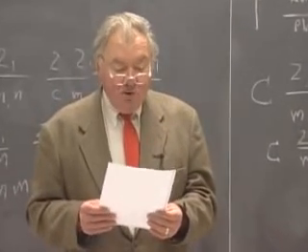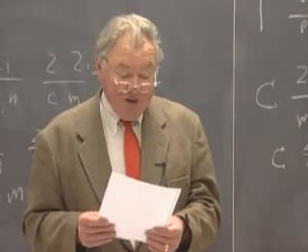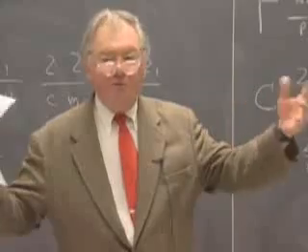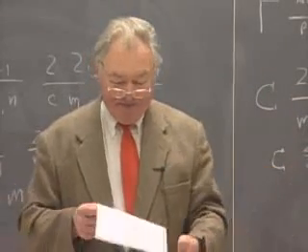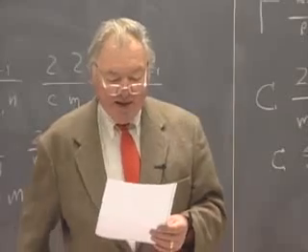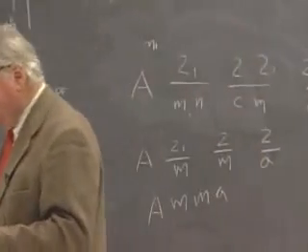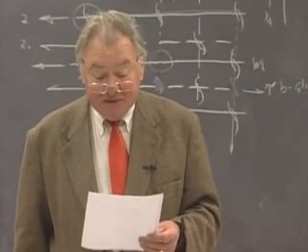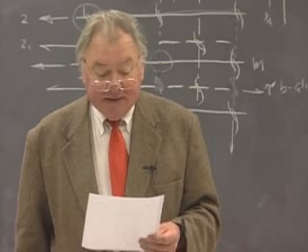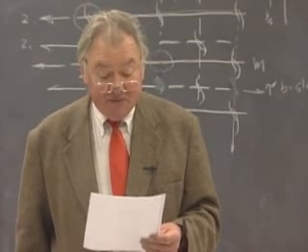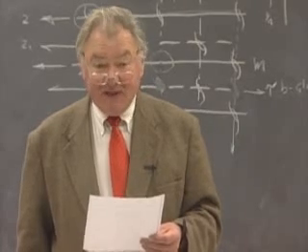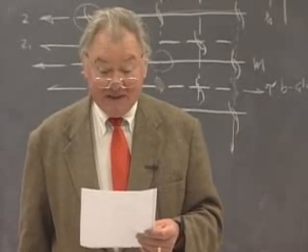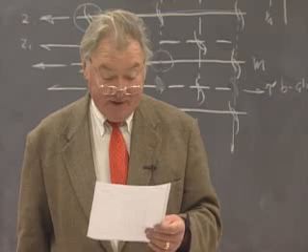You'll notice also the enormous number of atoms in the general position. 96 atoms. Drop in one atom at x, y, z, and woof, all hell breaks loose. You get 95 other atoms. And again, when the lattice is centered, they do not list all 96 sets of coordinates. They denote at the top of the page 0, 0, 0, 1 half, 1 half, 1 half plus. That means because the lattice is body-centered, to those 48 positions that are listed, you add 0, 0, 0, which is easy to do, and then add 1 half, 1 half, 1 half to x, y, and z, and these are the atoms that hang at the centered lattice point.